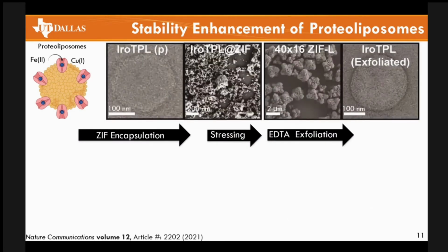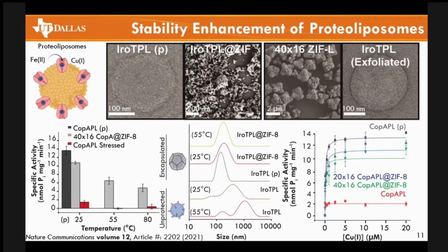And the experimental design was extremely straightforward, as we did with the blank liposomes. The idea was just to grab these proteoliposomes, encapsulate them, stress them, and then exfoliate them. After exfoliation, the idea was to study their structure and their transmembrane protein capabilities to see whether or not the ZIF had indeed protected them against these harsh environmental conditions. So again, we tested 25 degrees room temperature for 48 hours, 55 degrees Celsius for 15 minutes, and 80 degrees for 5 minutes. CopA is a copper transporter, and we were able to, after exfoliation, quantify its copper transporting capabilities.